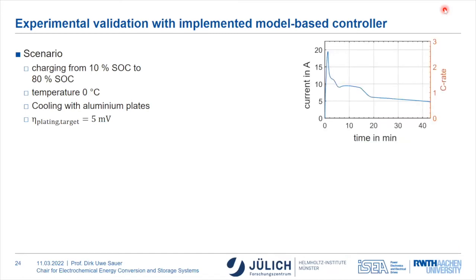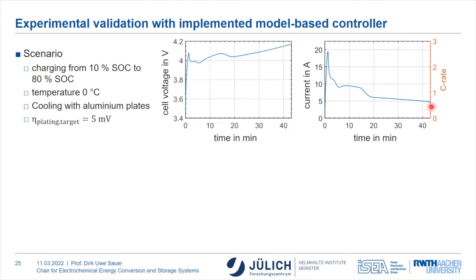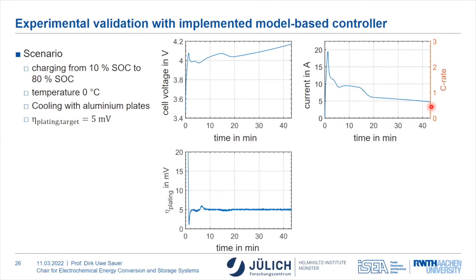And here you can see such a charging process. In the upper right hand figure, you can see the current which is flowing here. So it's an approximately 8 ampere hour battery cell. And you can see at the beginning, it can be charged at relatively high current, but then towards the full charging for sure was decreasing current. This is the cell voltage. This is what we can measure with a battery management system without any problem, but which obviously does not hold the information we need, because the information we need is this potential of the negative electrode. And here you can see we have put the control value to 5 millivolt above zero. And the controller keeps the voltage of the anode according to the model output for sure, quite precisely at these 5 millivolts just at the beginning.